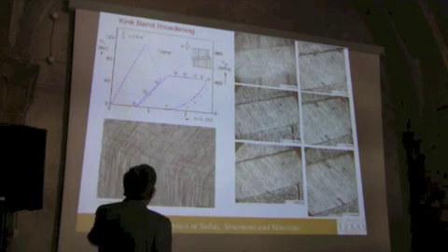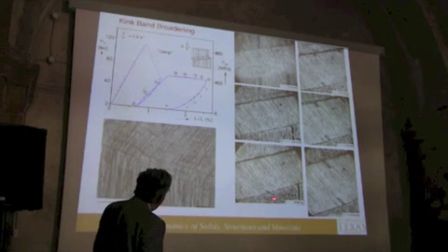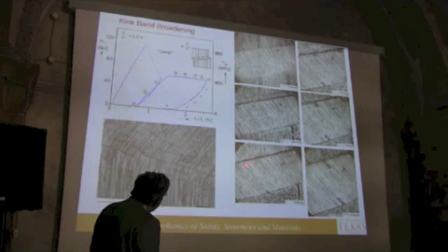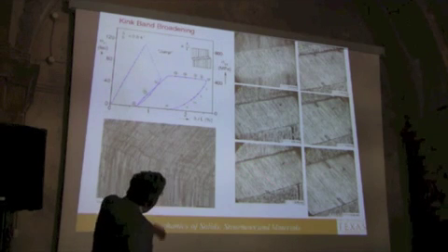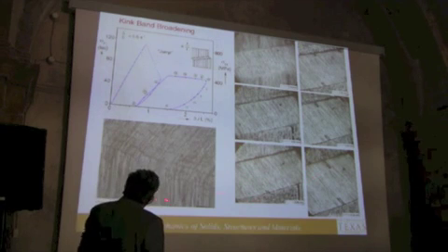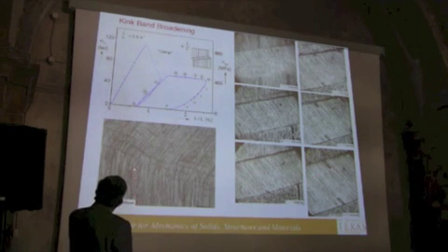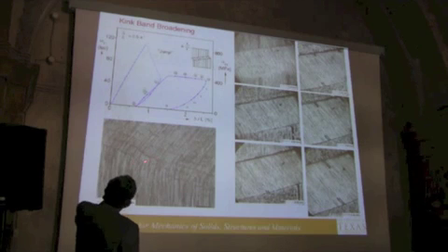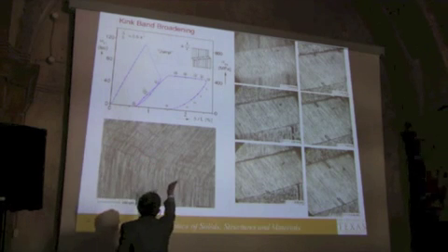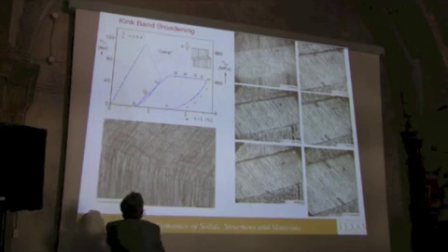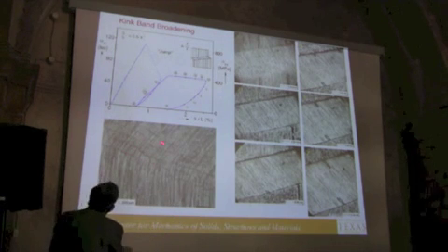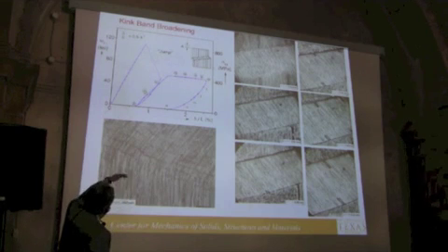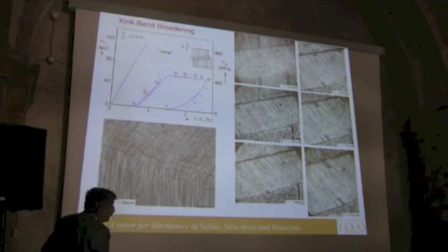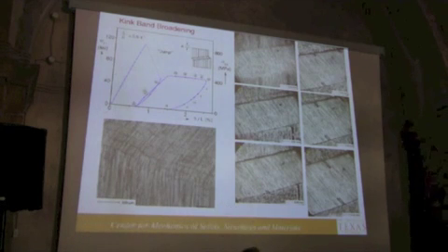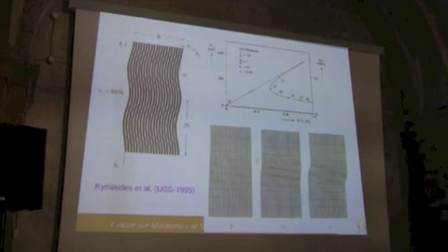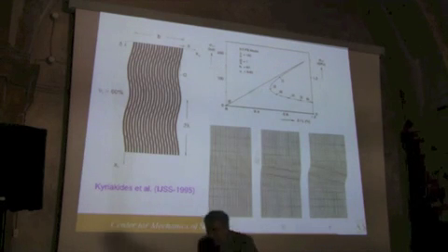Okay, now, if you look at this, these are straight fibers, and these are bent, these are inclined fibers. So if you look at the transition here, what's happening is that you are feeding in fibers, you are bending them locally here with a little curvature, and when they bend enough, they break, and you see these breaks that propagate, and that's really what's in here, a bunch of breaks. I have a movie, but it's better if I move on.